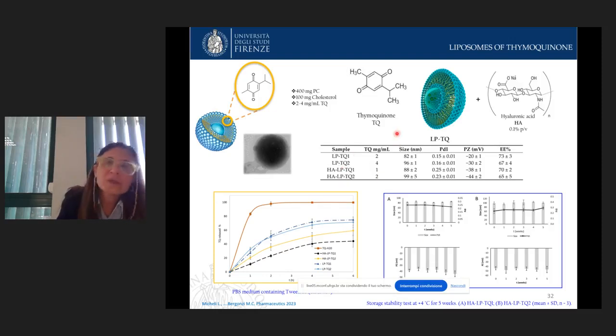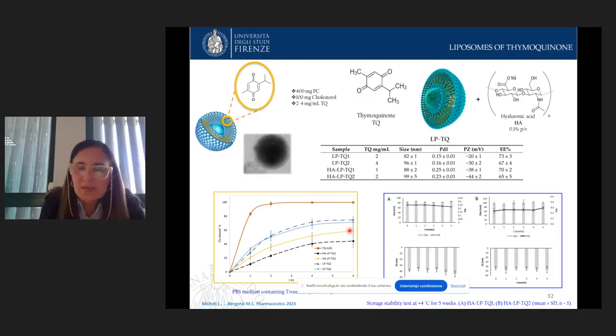In the same way, we characterized the carriers from a physical and chemical point of view. We studied the release of thymoquinone from the carriers, and we observed that the liposomes realize a prolonged release with respect to the release of thymoquinone from a solution. In particular, the presence of hyaluronic acid around the carrier, in this case, produces a reduction of drug release. This is due to the presence of hyaluronic acid, because there is first a hydration of the coating and then a release of the drug. This hydration process produces a slow release of the thymoquinone.